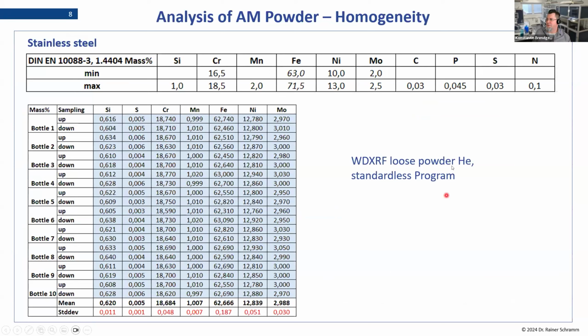So in this one, we can see we made the homogeneity test, basically taking different bottles from the same charge, and we just looked at the measurements. We used a standardless software for these measurements, and this was one of our wavelength dispersive XRF machines under helium. So we basically filled it in a cup and measured it standardless. And as you can see, the homogeneity of the powder is really good. That mainly comes from, or the explanation would be that this is an alloy which is homogeneous, and it is prepared in a special way to give us this very specific particle size.